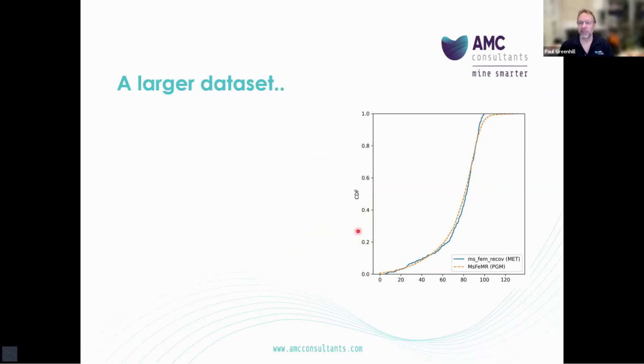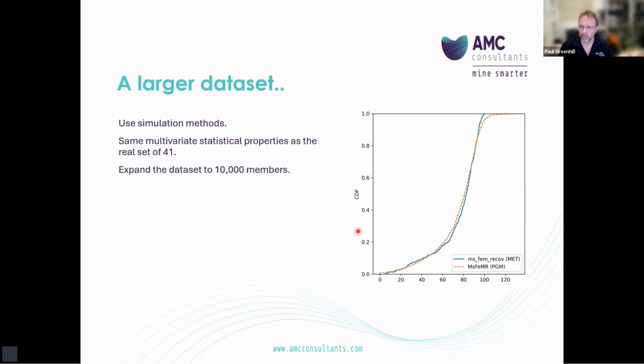So generating a sufficiently large data set for testing can be done if we can preserve the properties of the real data set. So we're going to use a tool called a probabilistic graphical model to do this. And that's a tool that will generate an expanded set of data with the same multivariate statistical properties as the original. The figure is a cumulative distribution plot showing a comparison between the original small data set and the enlarged data set. And when we're using this tool, it's very important that these CDF functions overlap as closely as possible. That indicates to us that we have a reasonable expansion of the data set with a consistent set of properties. So this is the way that we can expand the data set. In this case, we've expanded it to 10,000 members.